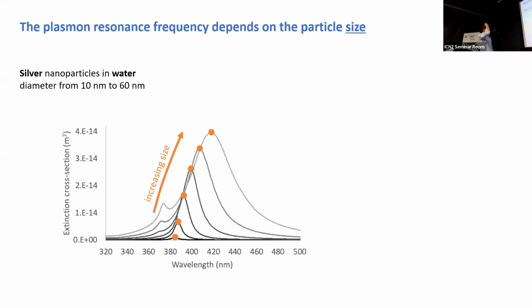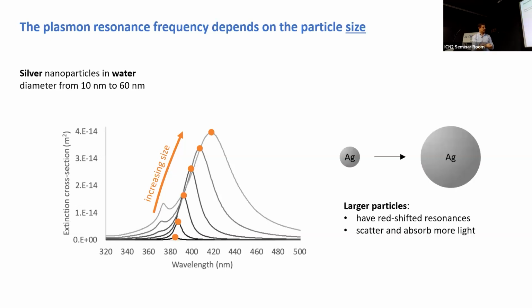So for example, the plasmon resonance frequency depends on the particle size. You take a silver nanoparticle, in water in this case, you vary the diameter from 10 to 60 nanometers, and you will find that your plasmon resonance shifts from around 380 nanometers into the red around 430. And it also increases because you have a bigger object, and the scattering and the absorption increase with the size of the particle. So larger particles typically have redshifted resonances and scatter and absorb more light.